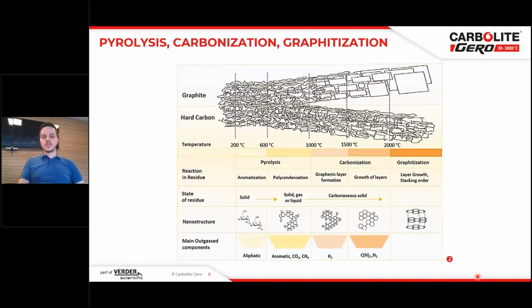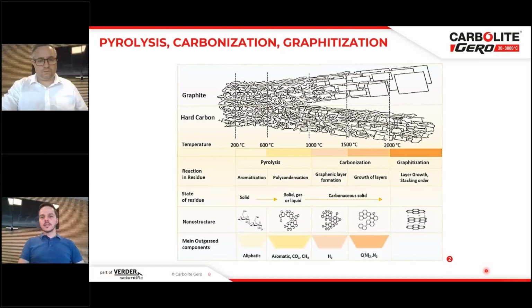At higher temperatures, which happens above 1000 degrees Celsius, also hydrogen is released and some CN structures or small CN molecules. Those volatiles cannot just be released to the environment, especially when you think of an industrial process. It would be a high amount of environmentally hazardous materials, so they should be converted with an afterburner, for example, into non-poisonous and non-toxic gases. It would be mainly water. Some CO2 will also be there, but this is not as dramatic as methane in this case.